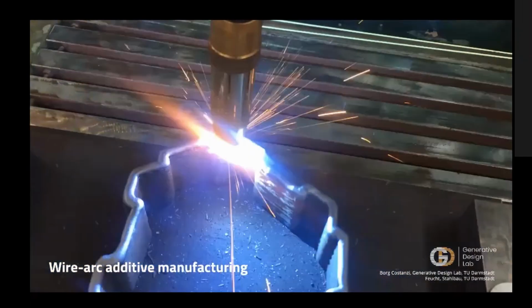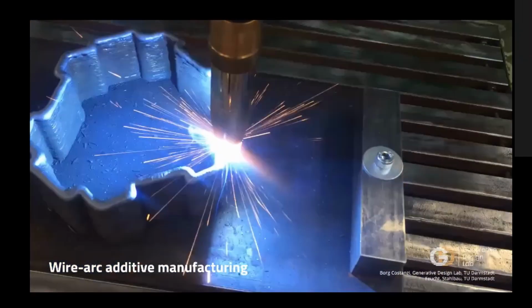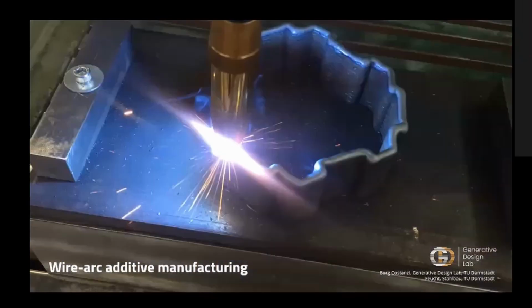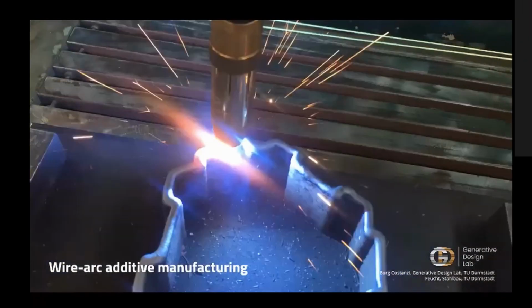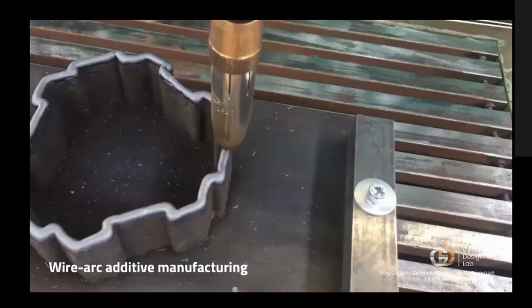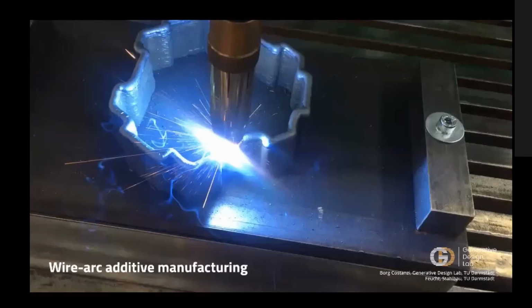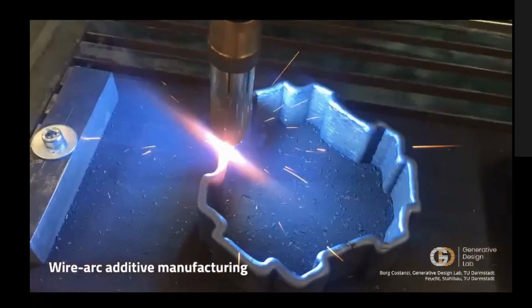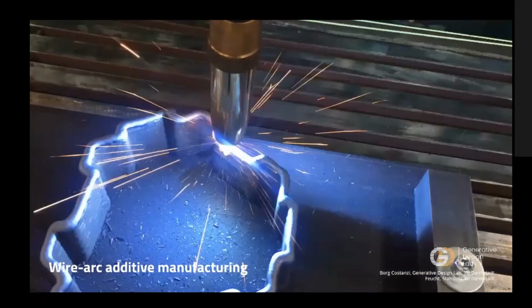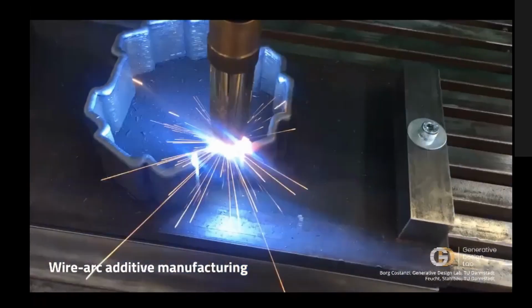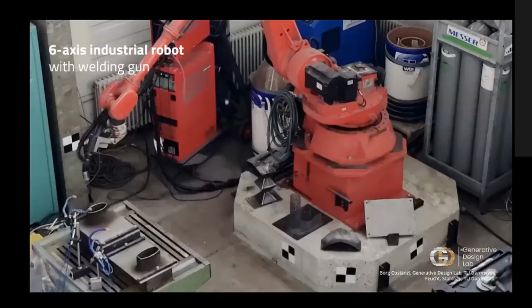Big plus of this technology is that it can feature deposition rates of up to 10 kilograms of material per hour. And it's open to a wide range of materials, not just steel that we're using, but also aluminum, titanium, you name it. The material is deposited either continuously, as shown here, or point-wise, as we will see in a later example. The setup that we use at TU Darmstadt is again a 6-axis industrial robot, and it's equipped with a welding gun. In this picture, you actually see some of the samples that we print in the lab.